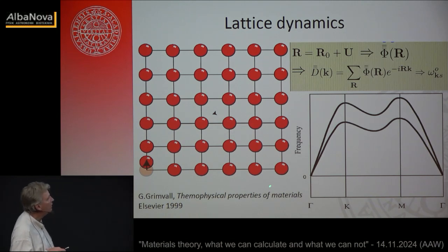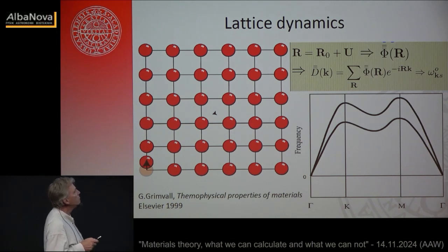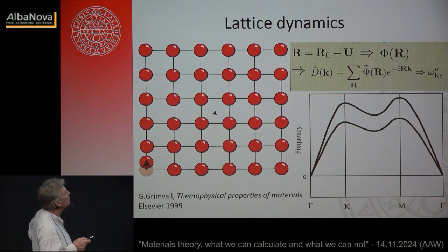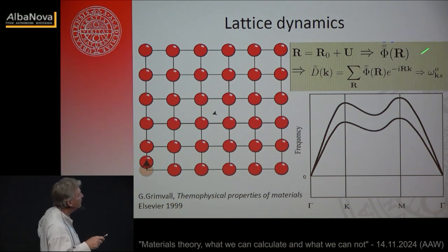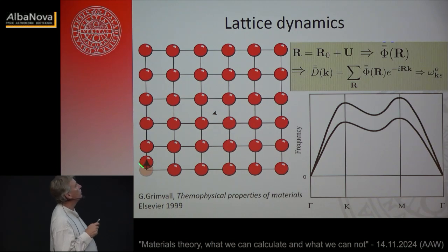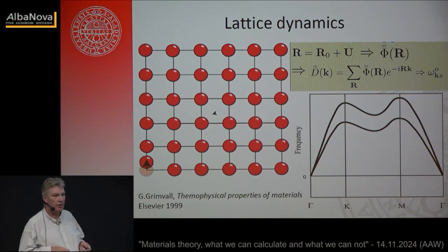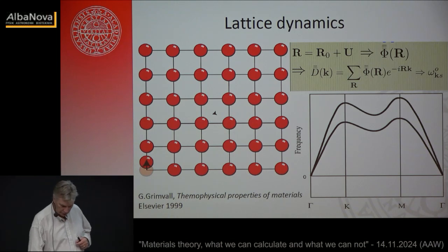This is accessible from measurements. I'll show you on the next slide how to do it. The crux of the matter here is you want to get a hold of this force constant matrix. You can do it in many ways, of course, but the way to do that from density functional theory is to simply calculate, from a larger supercell, the atoms in their equilibrium position, and then you move one atom a little bit up or down. That brings the system out of equilibrium and induces forces in all other atoms in the system, and that allows you directly to identify this phi here. So, large supercell, calculating forces in DFT calculations, and you have the phonons, and it looks like this.